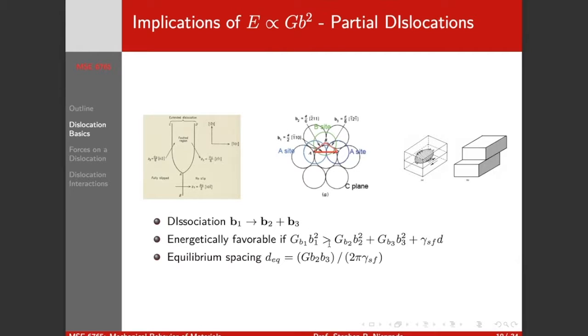And this is going to happen, is energetically favorable if the energy of this dislocation is more than this system. Now when this happens in FCC, you might remember you get a stacking fault - a stacking sequence. Instead of ABC stacking, we have an A site moves to, a B site moves to C site under the action of this partial dislocation in FCC. I will talk about this in class, but I didn't want to go into it in depth in the lecture part. But basically, in FCC, this is going to create a stacking fault here.